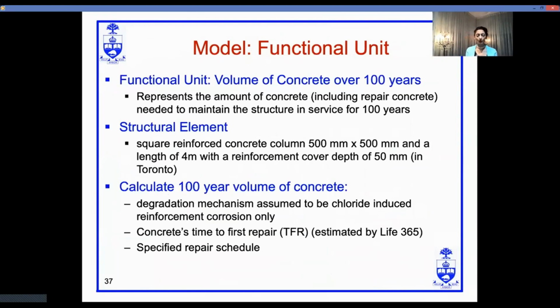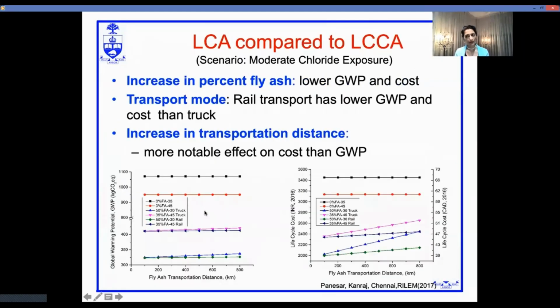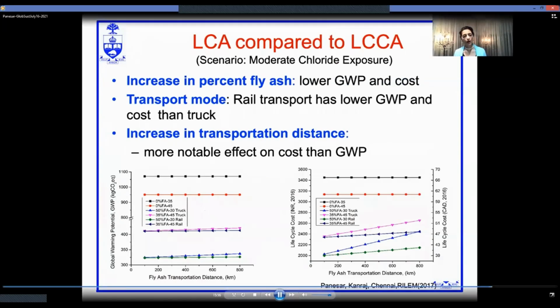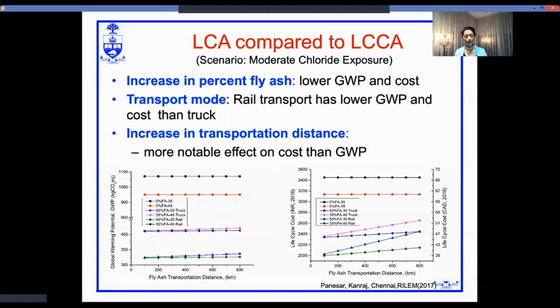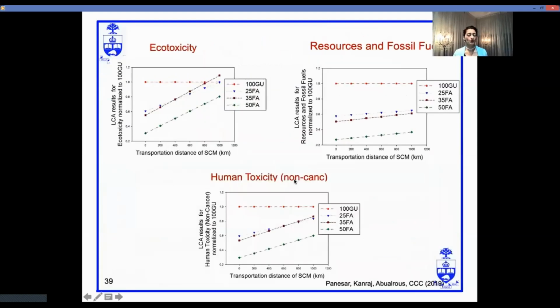Some more model details. The functional unit that we used in this study was the volume of concrete over the 100-year study period. Time to first repair was estimated using Life-365. And basically, when we compared our LCA to our LCCA, as we expected, increasing the percentage of fly ash lowered the global warming potential and the cost. One figure shows global warming potential against the fly ash transport distance. The other figure shows life cycle cost against transportation distance. Rail had less burdens compared to truck. Again, this is what we had expected. And with increasing transportation distance, there appeared to be a more notable effect on costs in comparison to global warming potential.